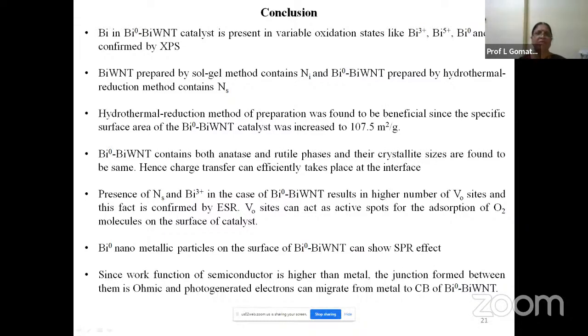And we found that the specific surface area of the sample prepared by hydrothermal reduction method was very high, 107.5 square meters per gram, and BiWNT prepared by hydrothermal reduction method had two different phases, anatase and rutile crystal structures, and they have similar crystallite sizes, 18.7 nanometers, and charge transfer can efficiently take place when the crystallite sizes are almost similar. These kinds of results we have published in our previous papers, and the presence of substitutional nitrogen results in higher oxygen vacancies, and this is confirmed by ESR spectra.